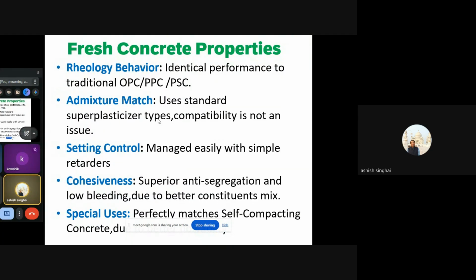What are the properties of fresh concrete made with LC3? First is rheological behavior. So identical performance to the traditional OPC, PPC or PSC. It is almost the same, but admixture match. So whatever kind of compatibility test we do with other typical OPC, PPC or PSC, the same kind of compatibility test with the admixtures and LC3 has to be adopted in the same manner. No other technology. Setting control is easily managed with simple retarders. Cohesiveness: superior anti-segregation and low bleeding due to better constituent mix.